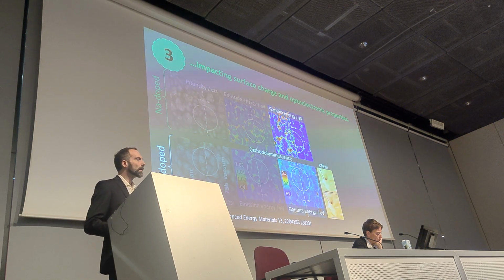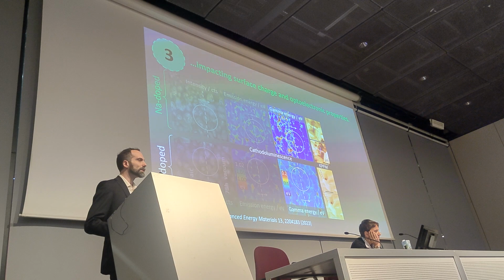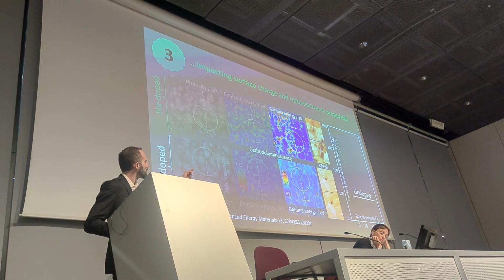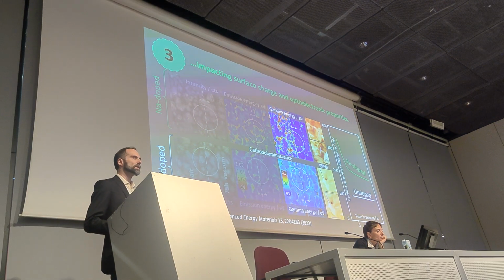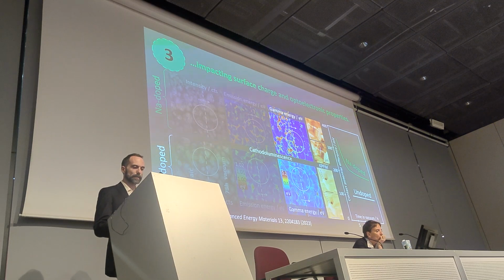We also perform Kelvin probe force microscopy measurements to assess what is the variation of the work function of the surface as a function of time during exposure to air. Again, nothing changes over a time frame of hours. My colleague got crazy doing this experiment in the very same location for 20 hours. But what happens now with the sodium doped case? We clearly see a variation of the work function over a time frame of 20 hours. This is not something physical, it's a chemical.